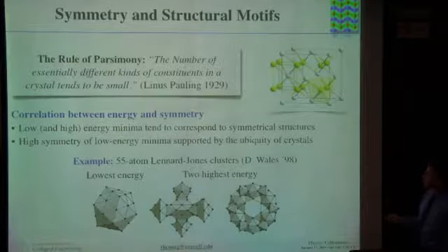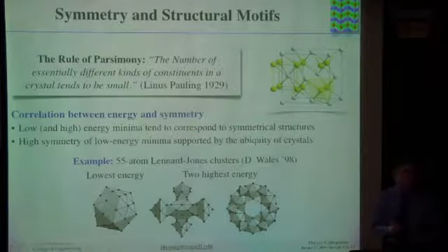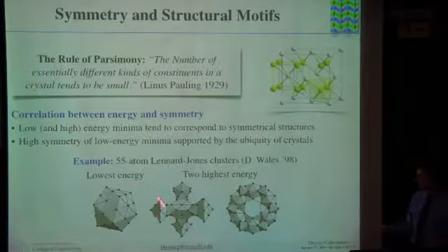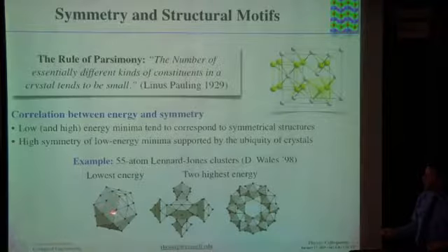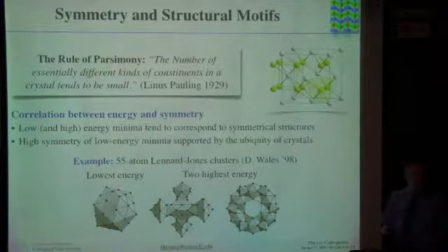Later, David Wales also showed there's a correlation between energy and symmetry, which generally holds, that often low and high energy minima tend to correspond to very symmetrical structures. He showed that specifically for clusters, and here's an illustration for a 55-atom Lennard-Jones cluster, where the lowest energy version of taking 55 atoms interacting with the Lennard-Jones potential turns out to be an icosahedron.